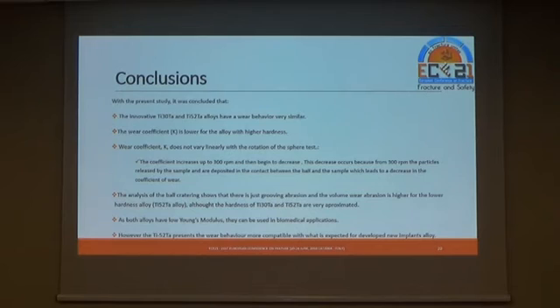The analysis of the ball craters shows that there is just growing abrasive wear, and the abrasive wear volume is higher for the lower hardness alloy, although the hardness of titanium 30% tantalum and titanium 52% tantalum are very approximate. As both alloys have low Young's modulus, they can be used in biomedical applications. However, the titanium 52% tantalum presents the wear behavior more compatible with what is expected for the development of new implant alloys.